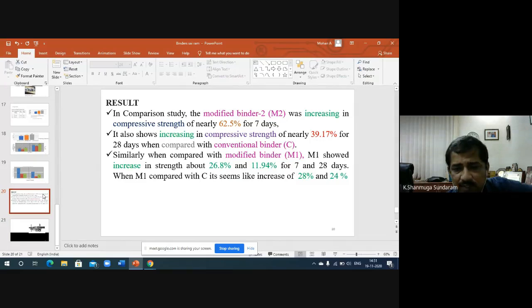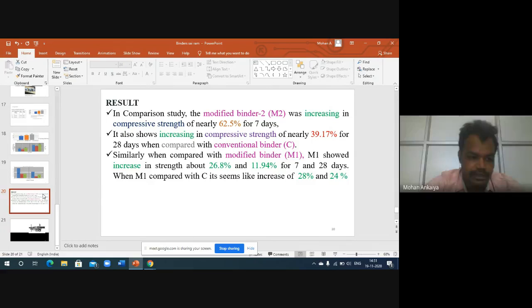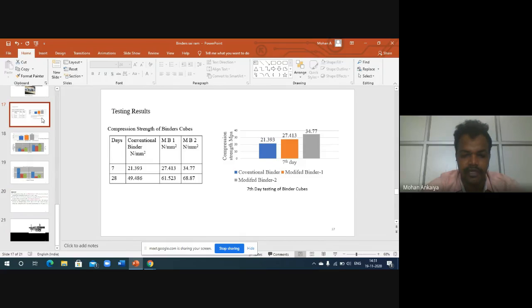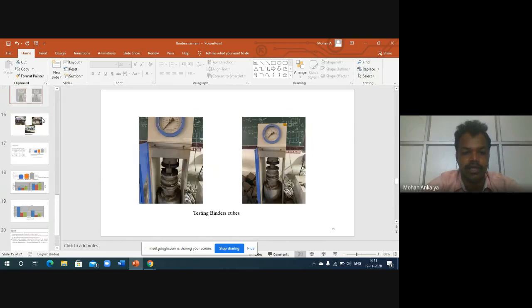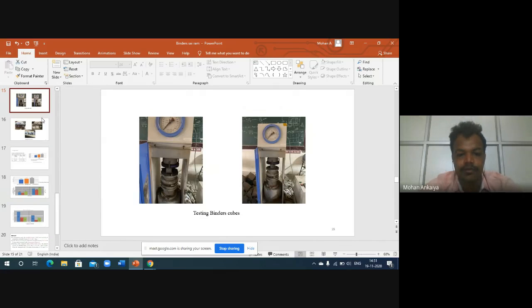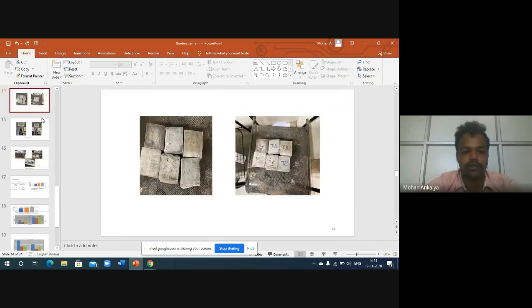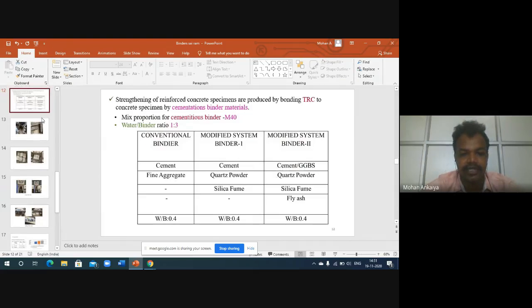Rather than just giving the quantified values, can you explain why it has increased by 62%? Yes, sir. As I said, for the increment of strength in concrete, the major two components are CaO and SiO2. The aggregate particles which have been adopted are rich in calcium and silica, sir. So this is the reason why both binders show the highest strength when compared to conventional binders.